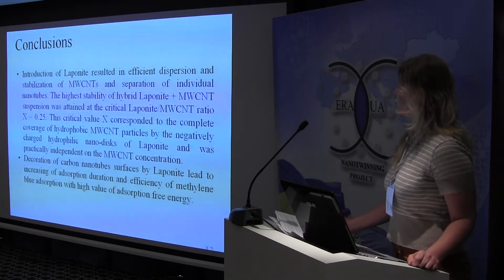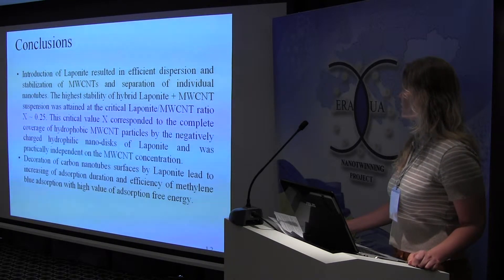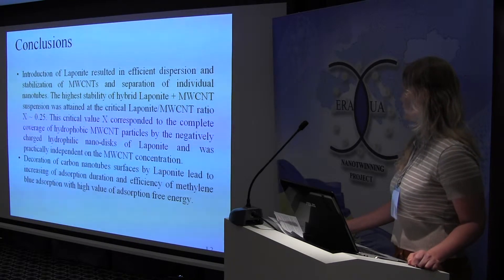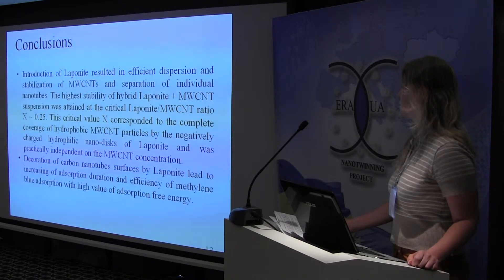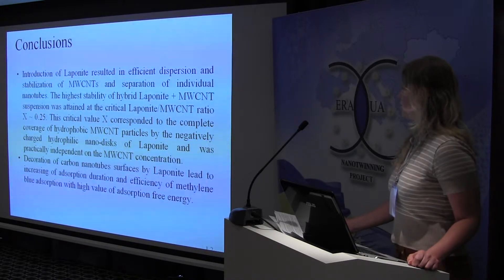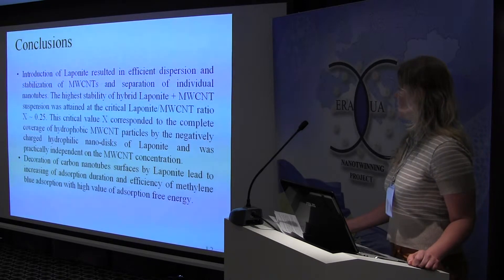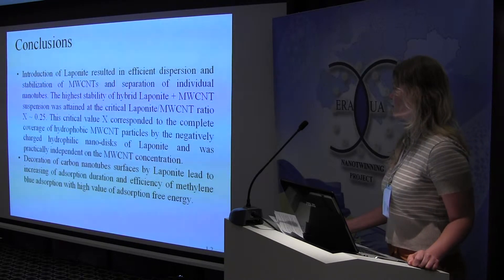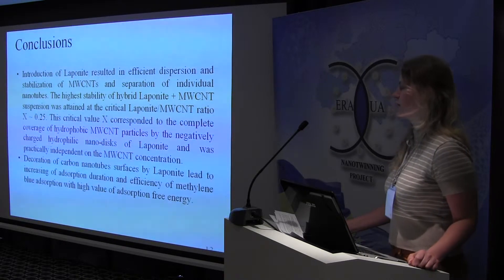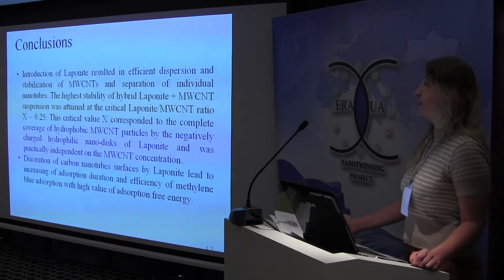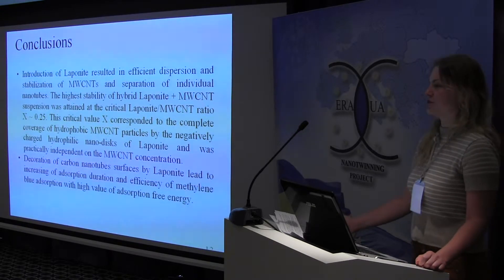In conclusion: introduction of laponite resulted in efficient dispersion and stabilization of carbon nanotubes and separation of individual nanotubes. Decoration of carbon nanotube surfaces by laponite leads to increasing adsorption duration and efficiency of methylene blue adsorption, with a high value of adsorption free energy.